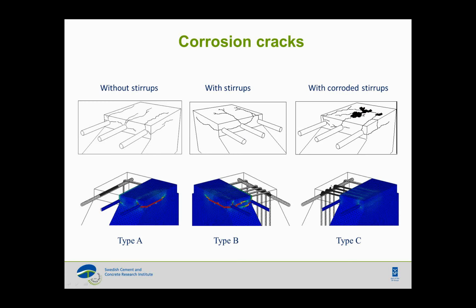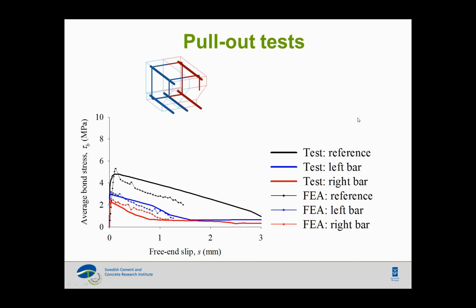And where we also have the stirrups exposed to corrosion, we have a very diffused crack pattern, and it's very difficult to capture that in the simulation. But actually we see that in the simulation we have cracks where we have the corroding stirrups. And to some extent that corresponds to what we see in the lab in the experiments.